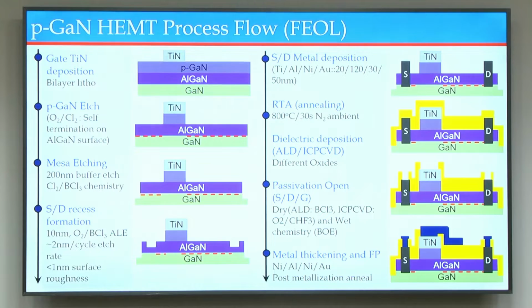So we have to develop a cyclic etch process where we can control the etch depth based on the number of cycles, and you actually program the number of cycles rather than the time for which you etch. The source drain metal deposition, okay, this is straightforward, but again the kind of ratios and the stack that you use for D mode would not work here, so you have to re-optimize this. The annealing conditions, since this is a recess device, a recessed source drain contact, the annealing conditions could be different.